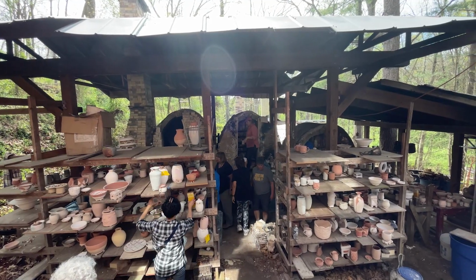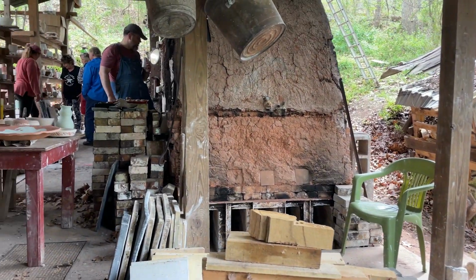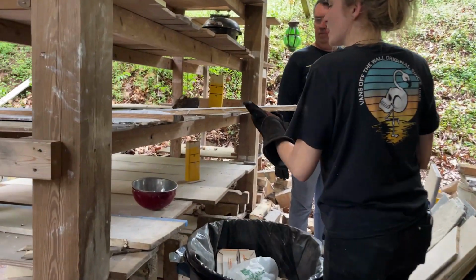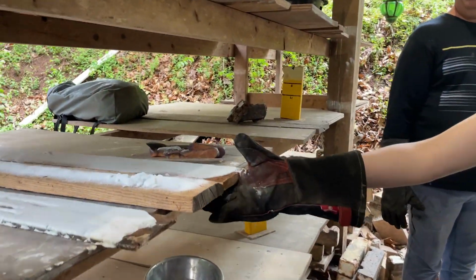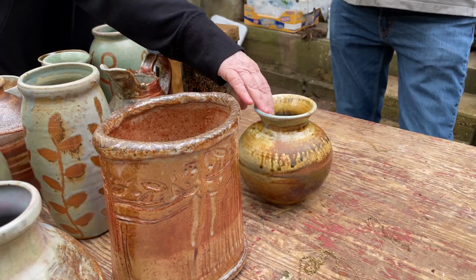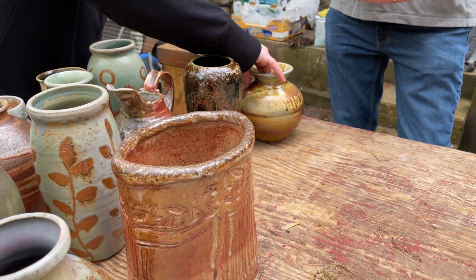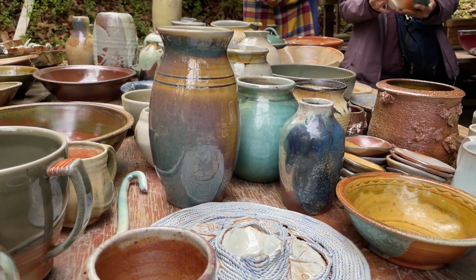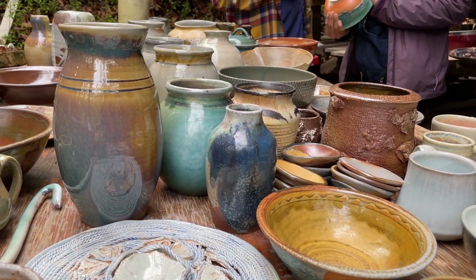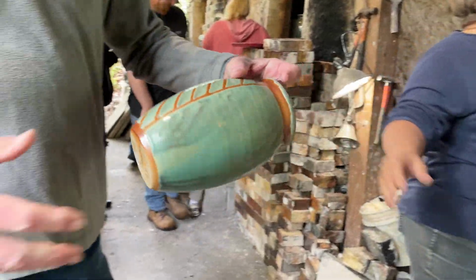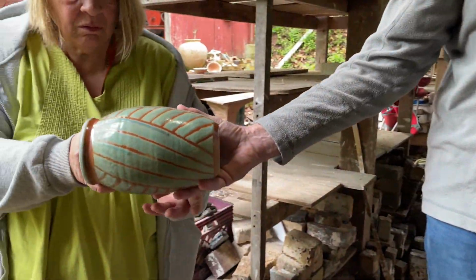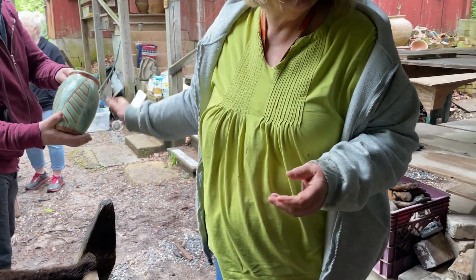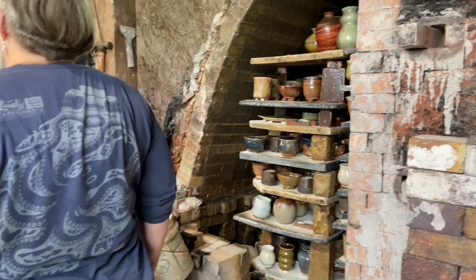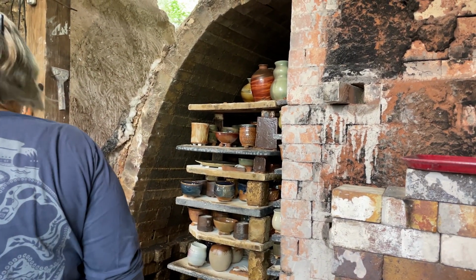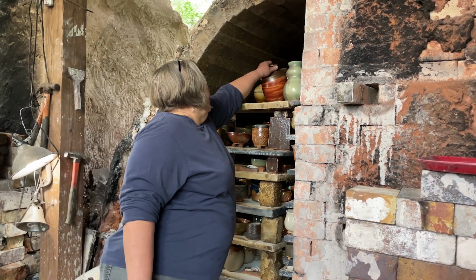There's 3 chambers to the kiln. The first chamber is only fired with wood. The 2nd and 3rd chamber also get salt and soda put into them, which gives the pots even more of a varied surface. The work is going to pick up a lot of its character from the atmosphere inside the kiln and the clay and the glaze's interaction with the fire. Every piece has its own unique relationship with the fire, and that gets recorded on the pot.